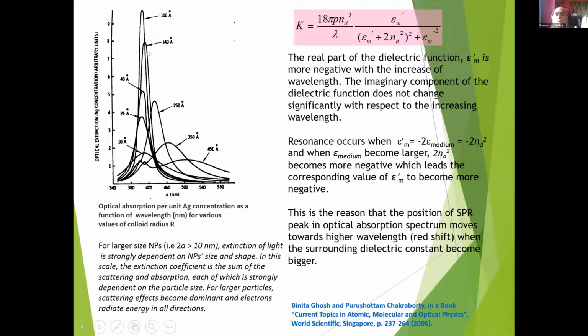This is the surface plasmon resonance, and we have calculated that metal particles of different radii have surface plasmon resonance at different optical wavelengths. But when the size of the metal particle is about 10 nanometers or even less, then the position of the peak doesn't change. I have to quickly go. This is coming from the Mie theory, of course.